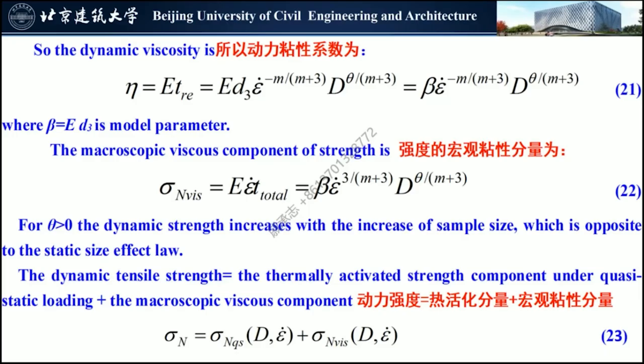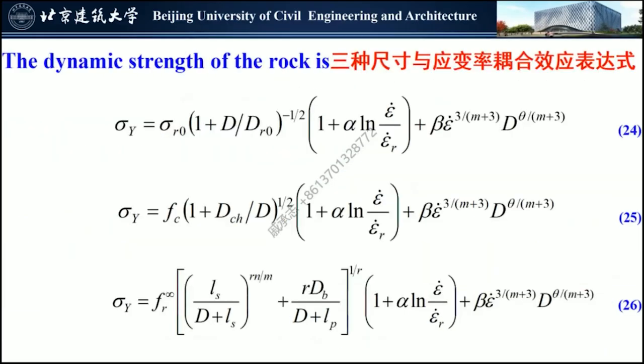For theta greater than 0, the dynamic strength increases with the increase of sample size, which is opposite to the static size effect law. The dynamic tensile strength includes the thermally activated strength component in quasi-static loading and the macroscopic viscous component, expressed by equation 23. Therefore, we have the following three kinds of expressions for the dynamic strength of rock.